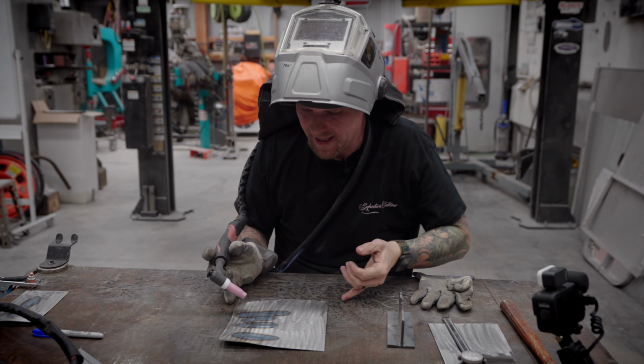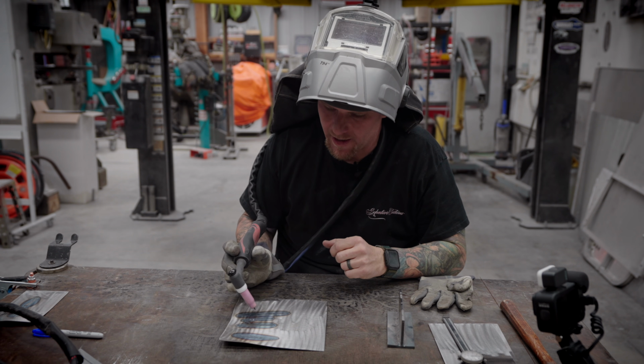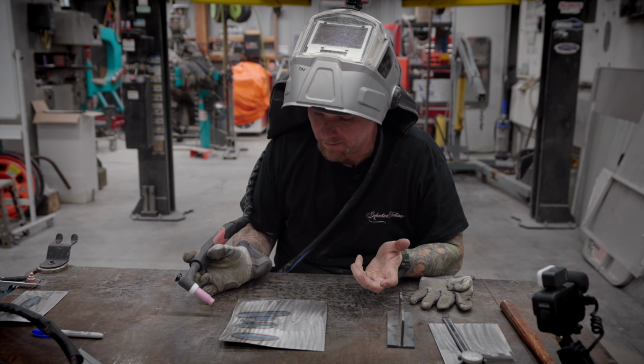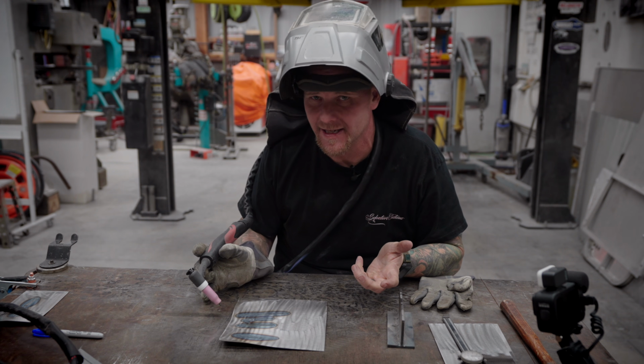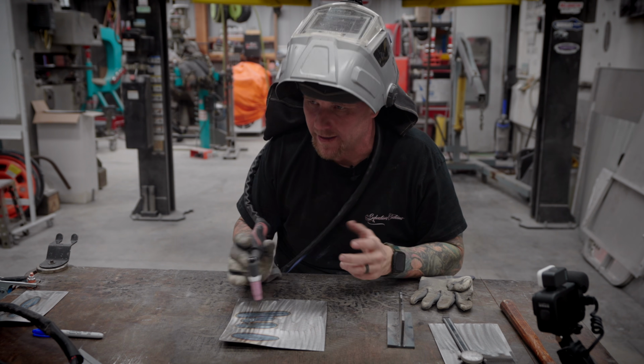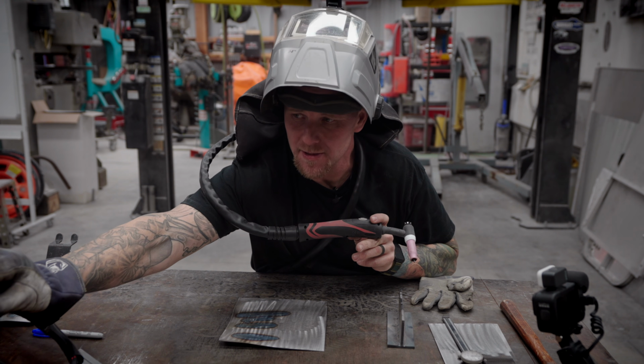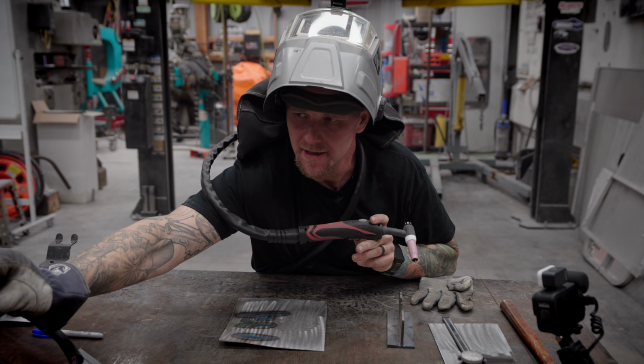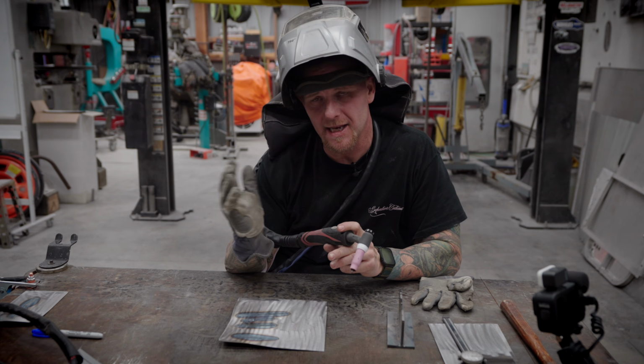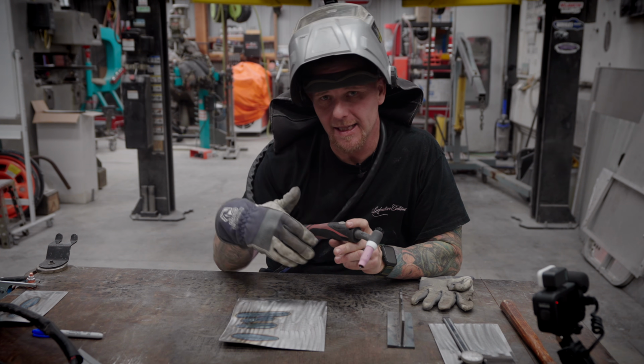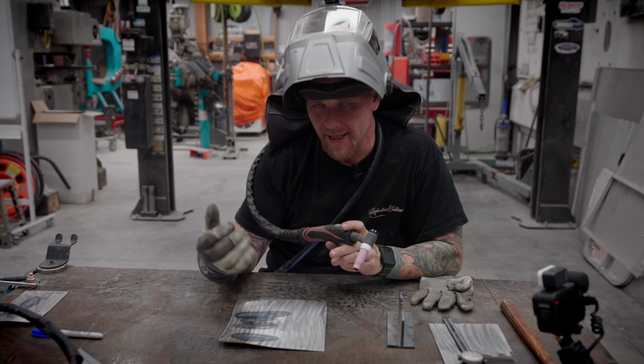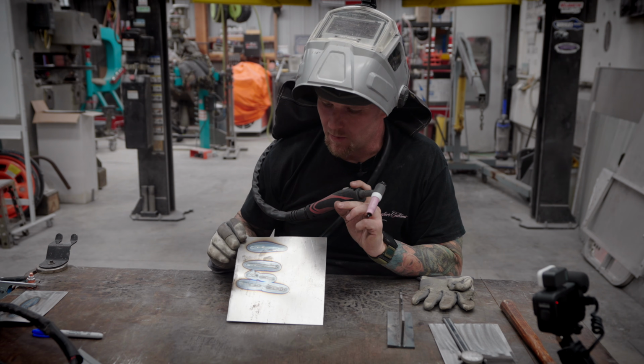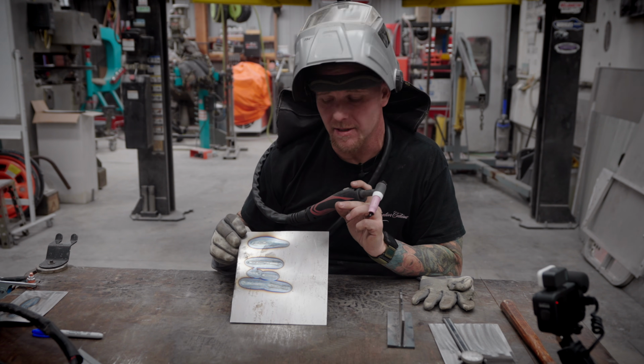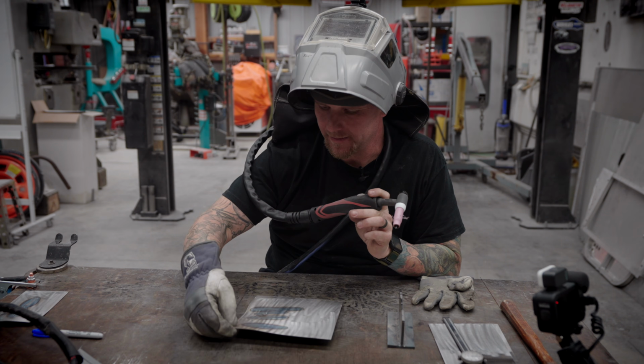And you can even see in the center here where we just don't have any puddle. It's very inconsistent, and that's not what we want. And that's even with 48 amps. So you can play with your amperage. Remember, I would rather have it slightly higher than slightly under, because we want it to penetrate. We also want to be checking the back sides of our welds to make sure that it is penetrating.